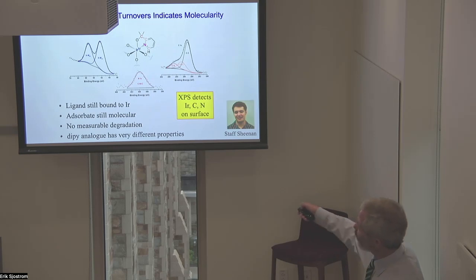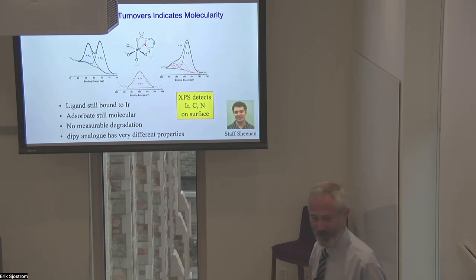He did X-ray photoelectron spectroscopy after about 100,000 turnovers, and looking at the iridium XPS signal, the nitrogen XPS signal, which is coming from the ligand, and the carbon XPS signal also coming from the ligand. And these XPS signals are virtually identical to what they were before the catalysis. So the complex is very stable. The ligand is still bound, still molecular. There's no measurable degradation, even after 100,000 turnovers. We actually carried out electrocatalysis for a month, and it would maintain catalytic activity for a month.